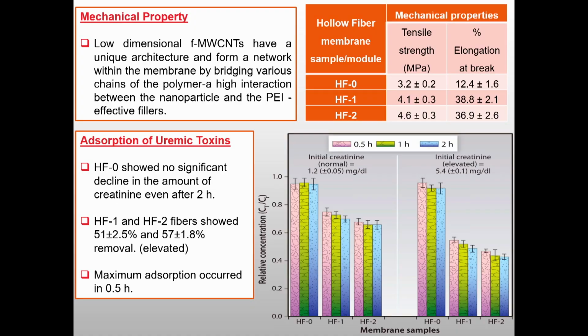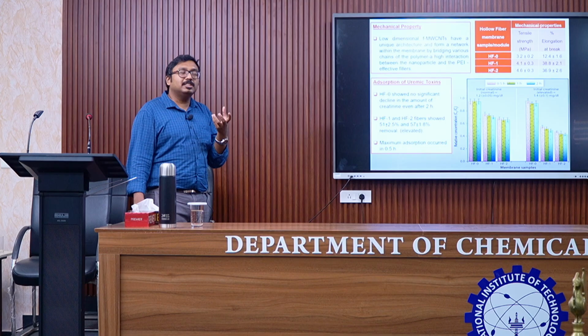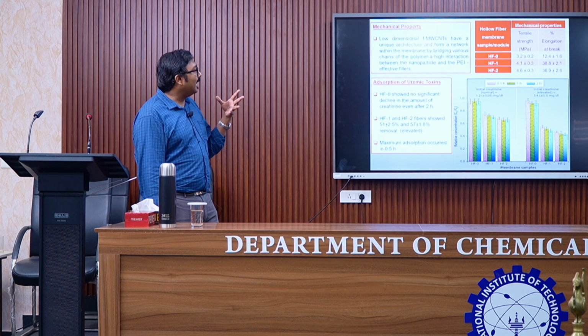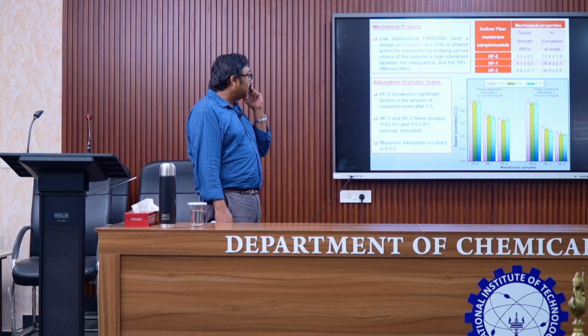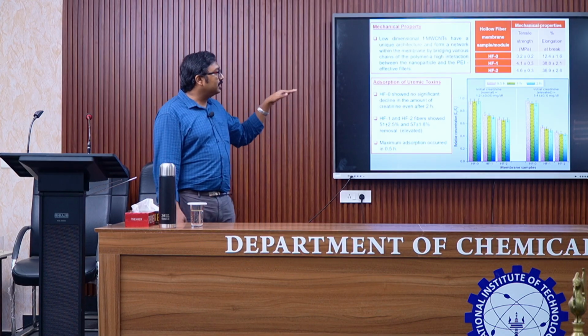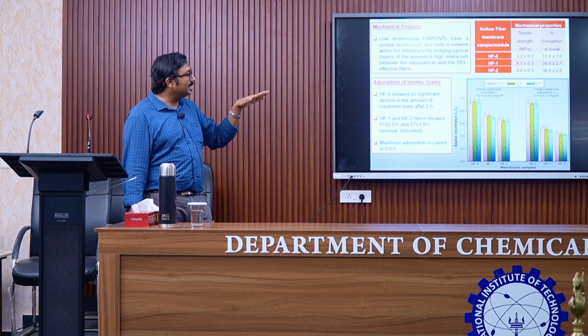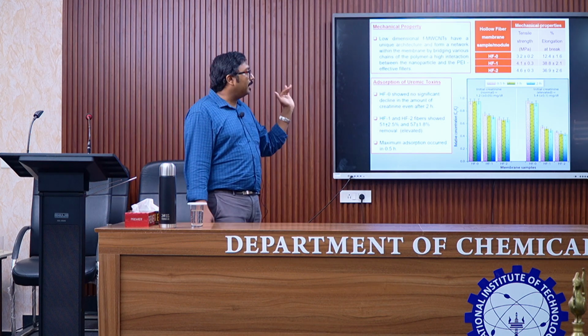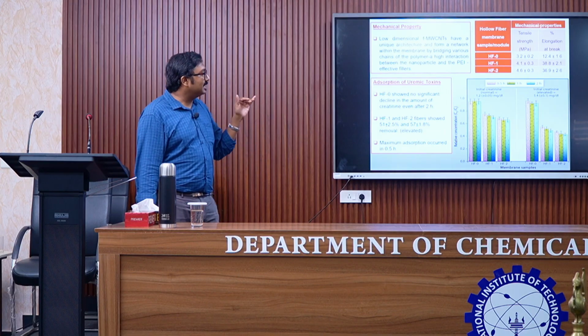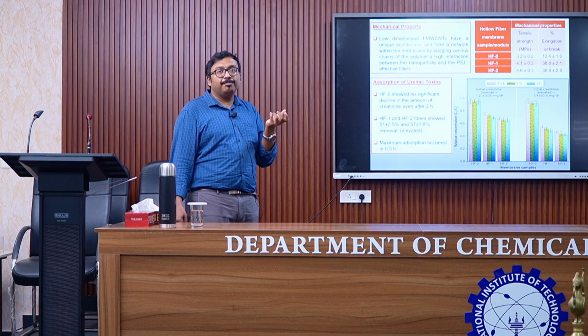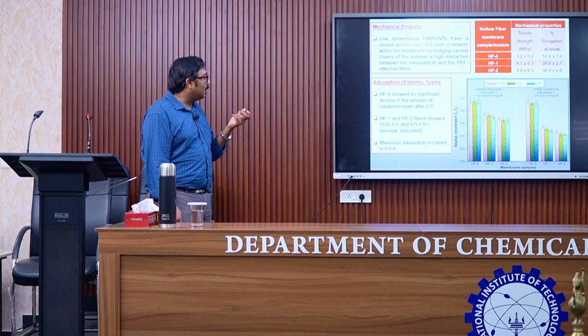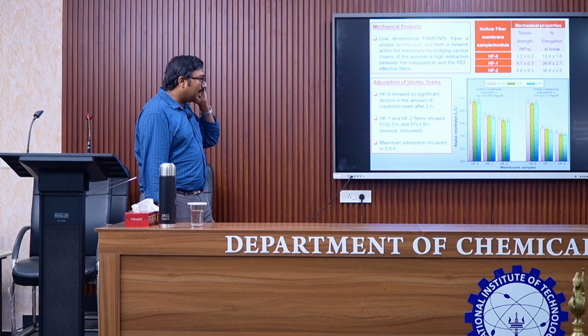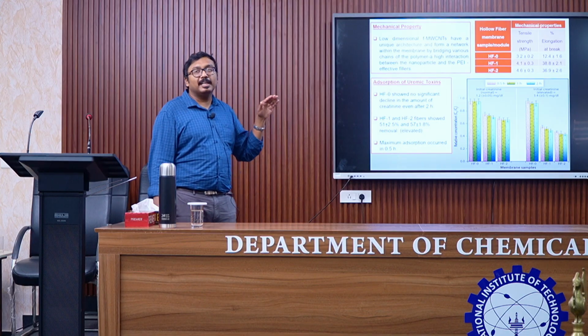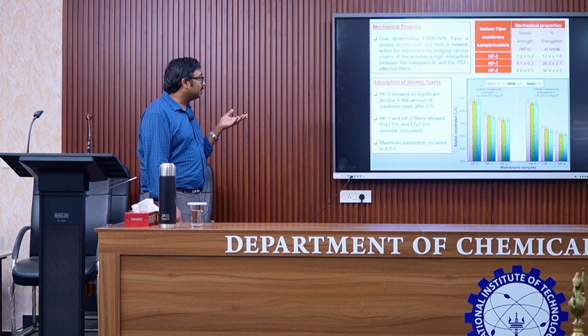And another additional property of these membranes was that they could adsorb toxins as well, because the carbon nanotubes acted as sites where it could particularly pick up creatinine. So we tested two levels of creatinine: the initial, normal level, around 1.2 milligram per deciliter, and a spiked one at 5.4 milligram per deciliter, and we saw that there was always an adsorption of the creatinine by the membranes.